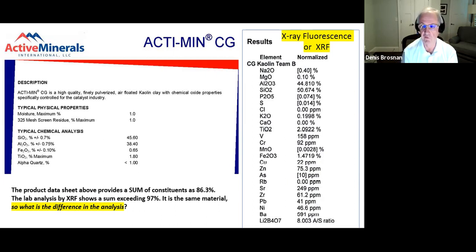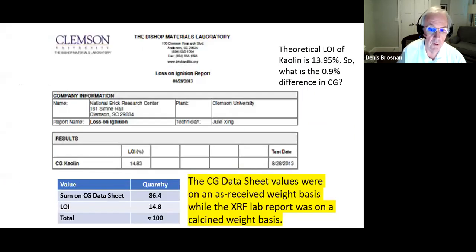So the key question is, what's the difference? Why does the active minerals product data sheet add up to about 86% and the analysis in my lab add up to 100%? Well, the answer is the weight basis that these numbers are expressed upon. So there's a test called loss on ignition. It's the loss in weight expressed as a percentage when a material is heated up, typically around the world, to 1,000 degrees Celsius, okay? 1,000 degrees Celsius will decompose most of the minerals that are present.